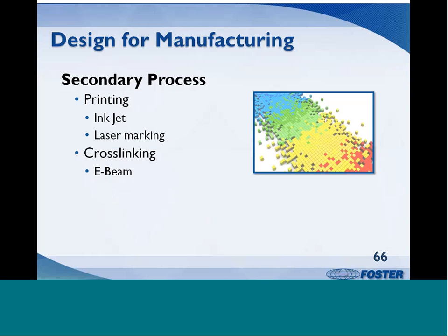Printing can be achieved by a few different methods. Inkjet inks can wet out better with some surface active agents built into the base resin. Laser marking almost universally needs to be color controlled and have some laser activated additives compounded in.